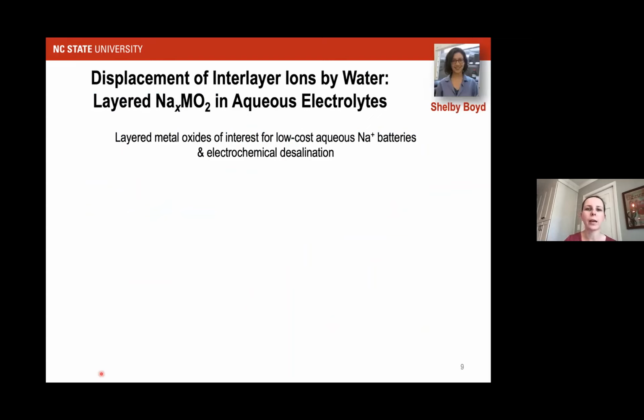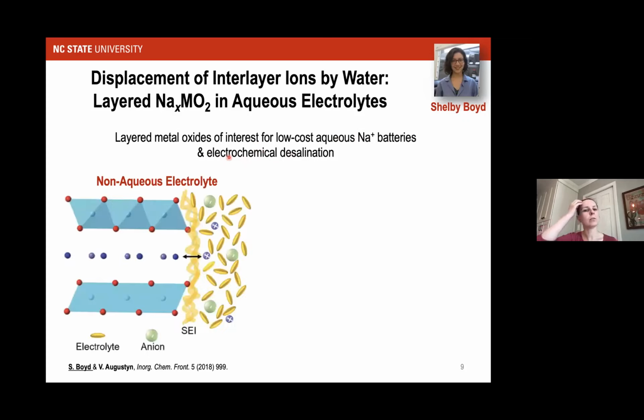It was actually a very interesting pathway. Shelby started her PhD where we wanted to look at layered metal oxides for low-cost aqueous sodium-ion batteries. And then because these materials would essentially be uptaking sodium ions from the electrolyte, that also would make them of interest for electrochemical desalination. And one thing to keep in mind is in the case of non-aqueous electrolytes, we oftentimes can think of this electrode-electrolyte interface as being rather sharp. So the interior of your layered material is not going to be really interacting with whatever's going on in the bulk of the electrolyte because desolvation energy barriers are relatively low, or you have the formation of solid electrolyte interfaces, solid electrolyte degradation products that essentially cause your cation to be completely desolvated by the time it intercalates into your material. And that's certainly the case. That's our operating picture for lithium-ion battery electrodes.